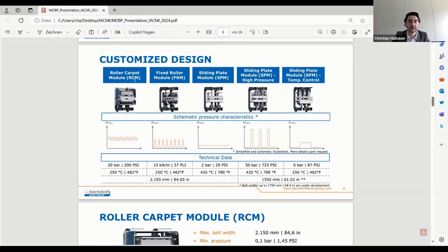Talking about composites in specific, for the thermoset-based composites, we would use the roller carpet module, which goes up to a pressure of 290 psi and 482 degrees Fahrenheit. Since usually thermoset-based composites require a constant pressure and temperature level, this is the model we would go for.